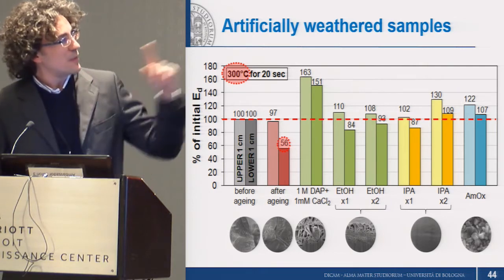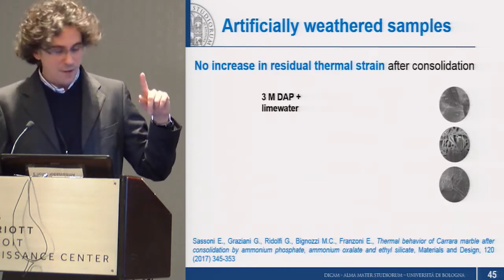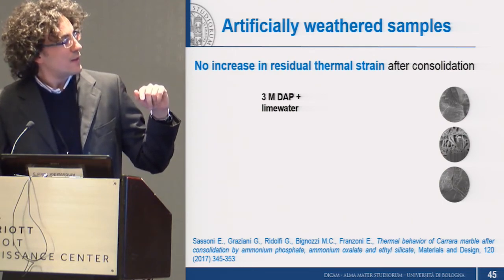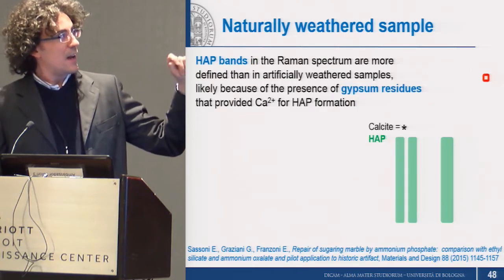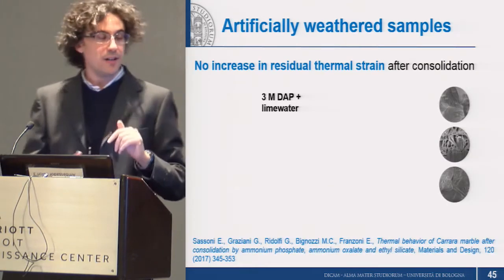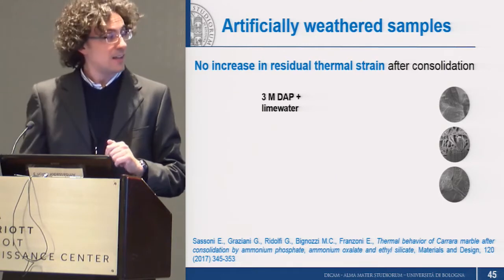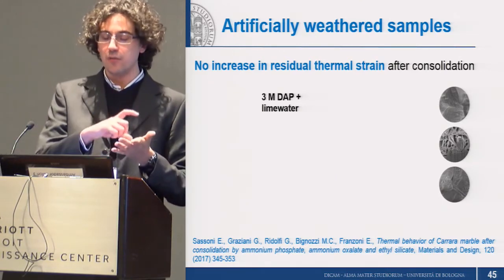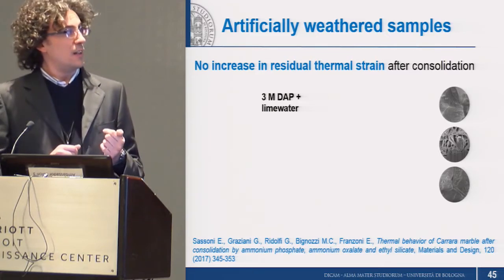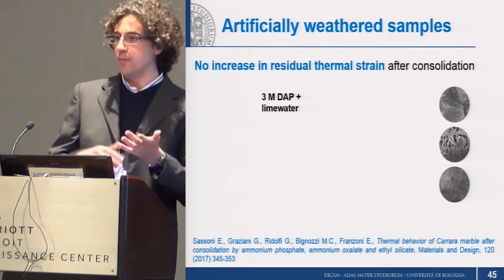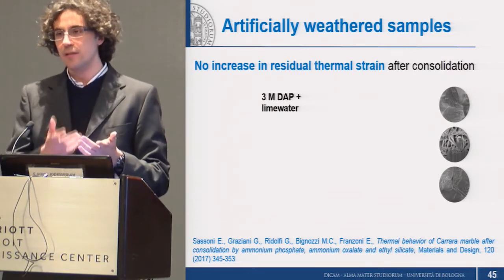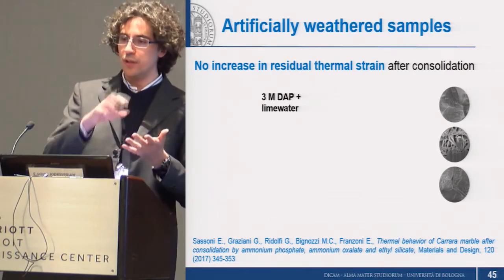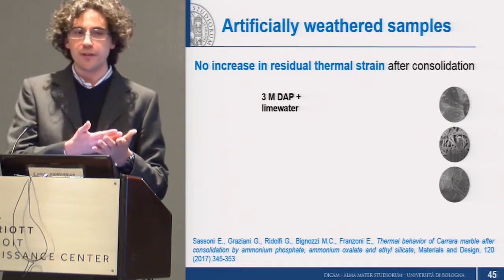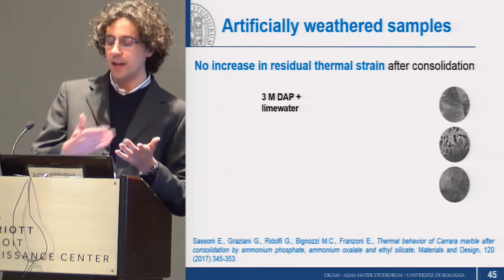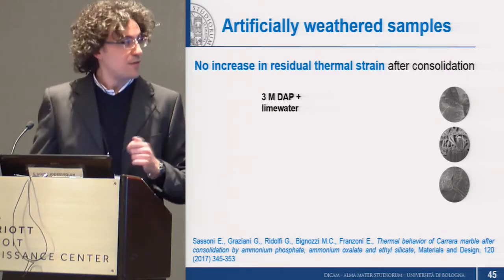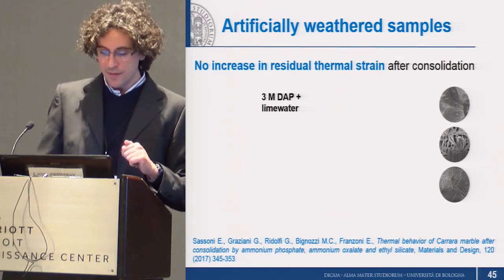Here, there are several figures that are missing, but were originally present. So in this slide, originally, there was the thermal behavior after the consolidation, and we could find that our treatment does not increase the residual strain of marble after treatment, which is important because with some commercial polymeric treatments, it was found that after consolidation with these polymers, the thermal behavior of marble got worse, which of course is undesired because as soon as the thermal cycles start, all the benefit is lost and marble undergoes a faster decay.